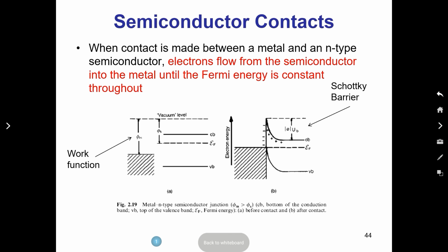Depending on the type of difference in work function, which is typically the amount of energy required to take an electron out of the material. So if you look at platinum, silver, gold, copper, etc., people have measured this work function. So depending on what metal you put on what oxide, you can create the so-called Schottky contact, or you can create a point.